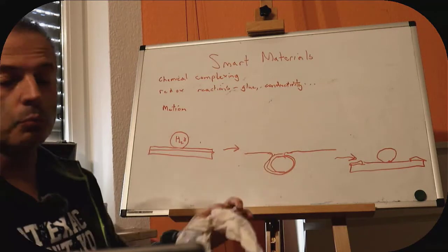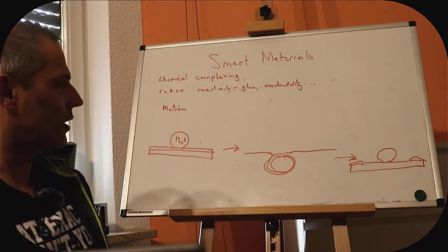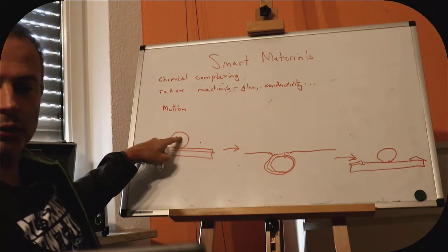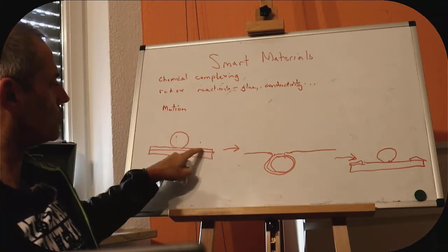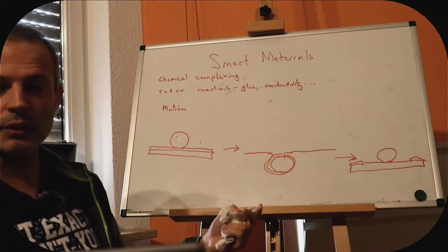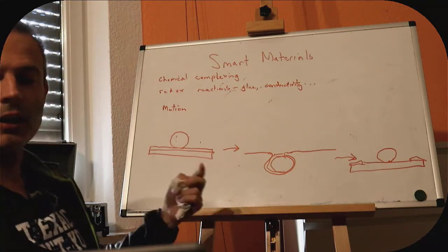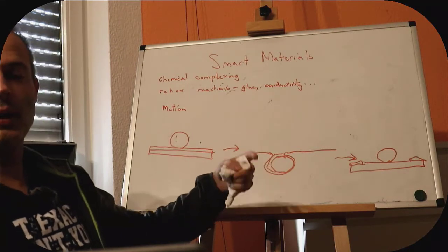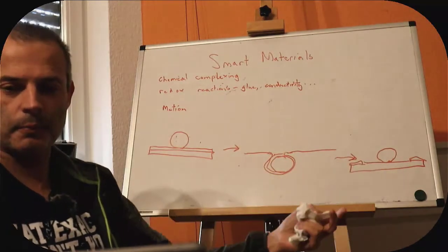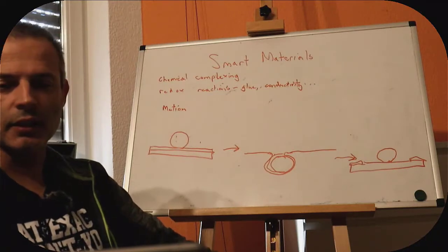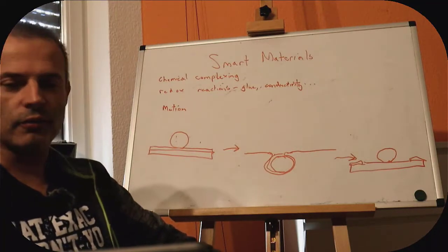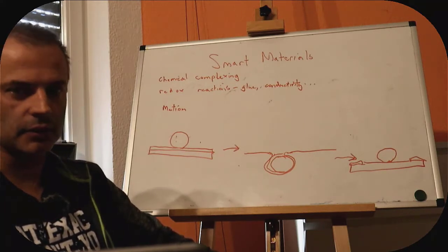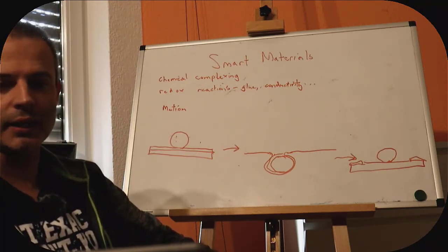So the more extreme example that I would imagine, and that I actually wanted to do, would be if you took this to be mercury, and this was a layer of gold, because for practical reasons it's relatively easy to cover a piece of PDMS with gold, and then you would get it to wrap up and let go very strongly, because the surface tension of mercury is very high, but it also doesn't stick very well to other things. It, in fact, sticks incredibly badly to other things.